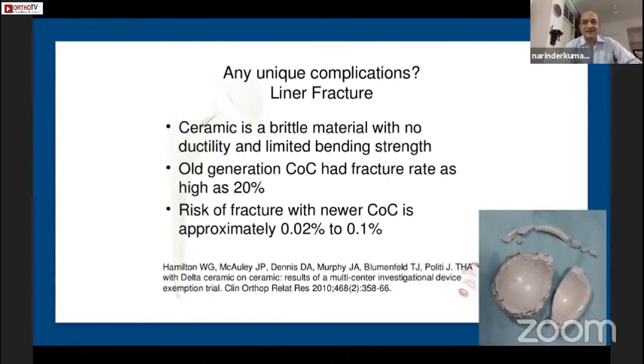But there are unique complications to the ceramics, where because ceramic is brittle material, those thin liners can fracture, especially while being inserted, because the taper junctions are still a challenge, which probably Martin will tell us about, what the taper junction challenge about the liners is. And the old generation, the first and second generation ceramic on ceramics had a fracture rate as high as 20%, which led to them falling into disrepute. But with the delta ceramic, the fracture rate has come down to less than 0.1%, which is absolutely acceptable.